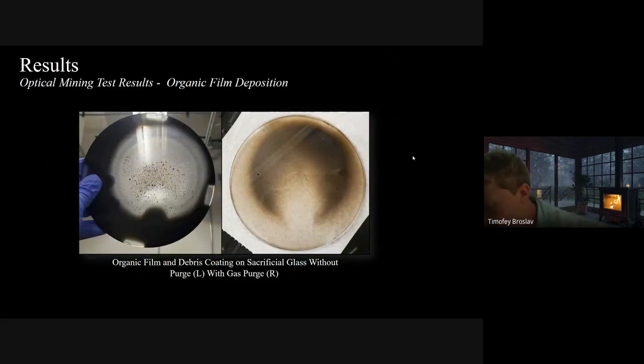Now here are all the results, both experimental and model. So one of the biggest challenges of this experiment, working with a carbonaceous simulant, is you're dealing with large organics that are heated, and they can deposit on surfaces within your vacuum chamber. And that's what occurred for the sacrificial glass you see here. We initially developed a carbon dioxide purge gas system to clean it. It did work. However, it did make things a lot more complicated, specifically for the test setup. And so we decided not to use it for further experiments.